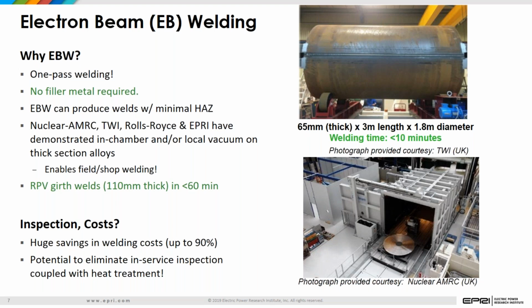Many of the current reactors utilize filler materials. Those filler materials, in certain cases, over time do tend to lose a little bit of their toughness. Because we're eliminating filler material, we do not have that drop in overall toughness or embrittlement. Electron beam welding can produce welds with a very minimal heat affected zone. And our goal in this project is to be able to produce 110 millimeter thick welds.